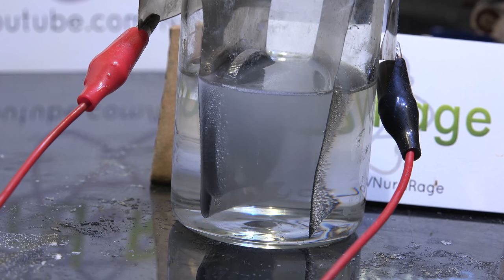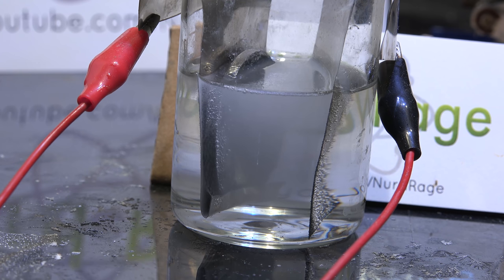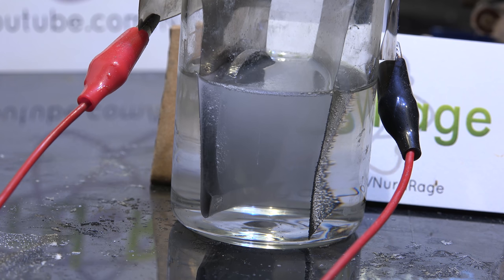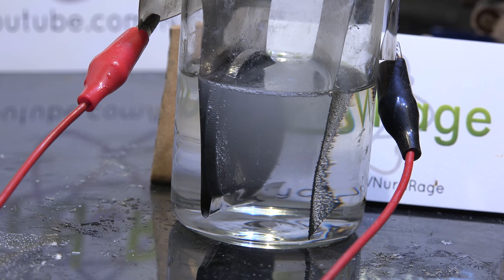I'm going to let this run for about 20 minutes to get nice thick layers of silver oxide and zinc metal. I'm not going to run longer because eventually the metals will get thick enough that they start to fall off. This is not a problem for a properly built cell that has a porous separator to physically hold the metals in, but for my demonstration cell that has no separator, the loss of metal means they won't contribute to any power that we may want to get back during discharge.